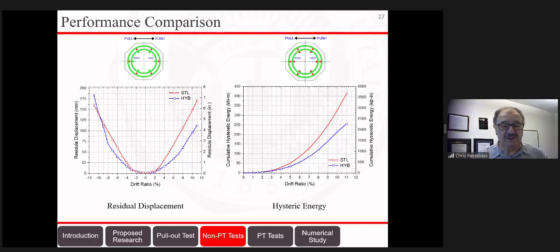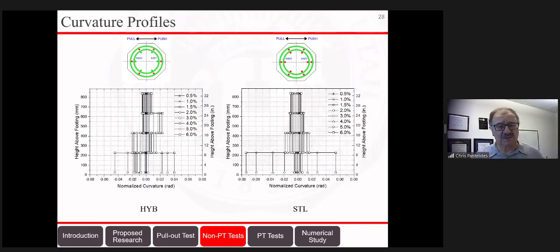One more thing we studied was the curvature profile. The curvature tells you how the column is actually performing during the test. So here in these graphs, you can see we have on the left the hybrid at increasing drift ratio up to 6%. After 6%, we had to take out the instruments so we didn't damage them.